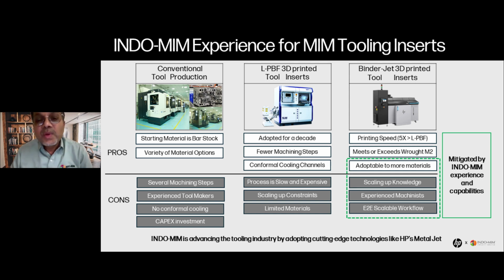So that is when we diverted our attention to 3D printing these tool elements using the binder jet process. Now the question is, why binder jet? Because LPBF and binder jet are both 3D printing processes, but the advantage with binder jet is that it is approximately 5 times faster compared to the laser bed. In a laser bed, you can probably print a build box in 3 days, whereas we can print a full build box in less than 10 or 12 hours.